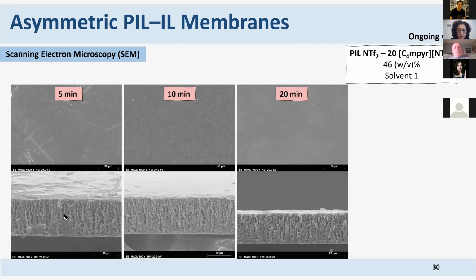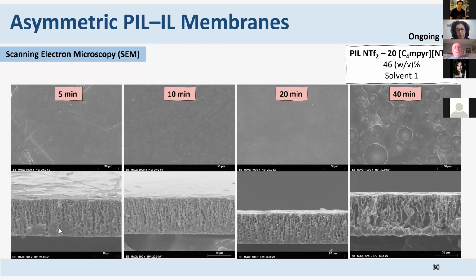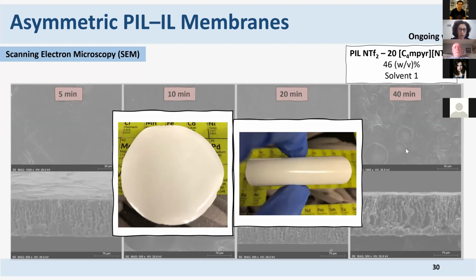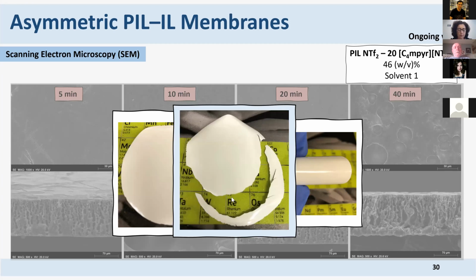This is after 20 minutes in the casting solution, and this is after 40 minutes, where the solvent starts to evaporate a lot and we start to have a very smooth surface. Let's take a look at the membranes. The membranes that we have been obtaining are quite nice, as you can see. They look very flexible, but when we put them in the apparatus, what happens is this. So they are in fact very fragile. So right now we are trying to solve this problem.